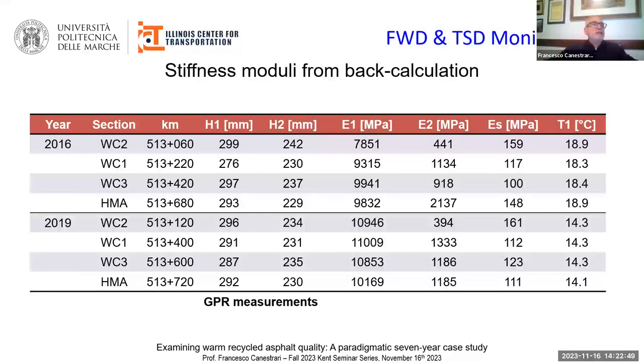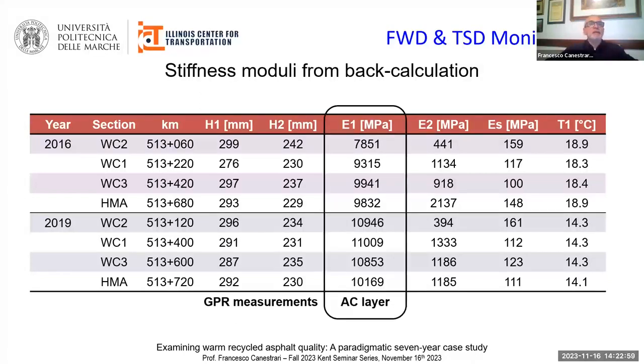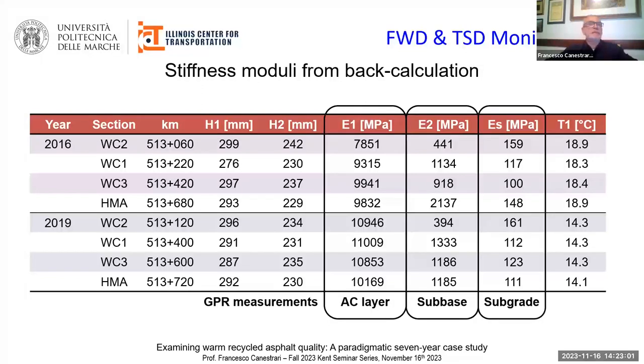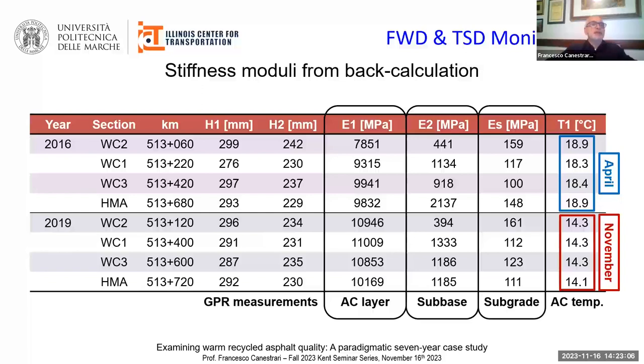The results of the back calculation are summarized in this table. For each test section, the table shows the stiffness moduli of the asphalt layer, the subbase, and the subgrade. The last column of the table indicates the temperature of the asphalt layer. We can observe that there is a difference of more than 4 degrees C between the 2016 and 2019 temperatures. For this reason, it was necessary to refer all the asphalt layer moduli to the same temperature equal to 20 degrees C.